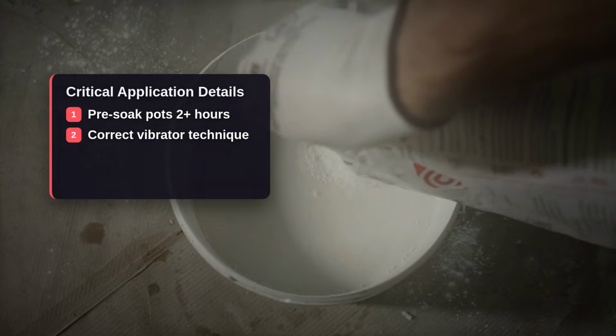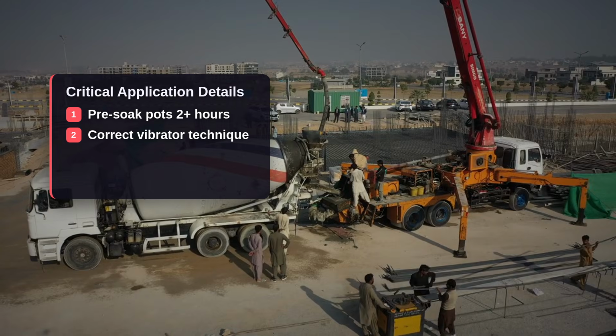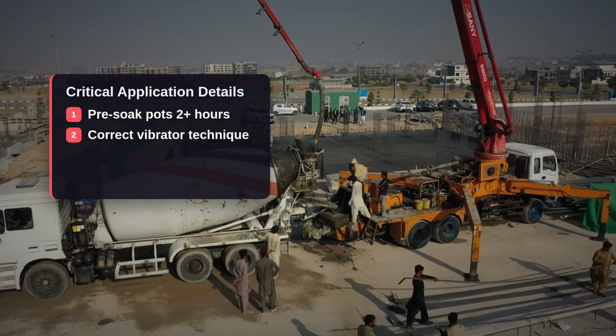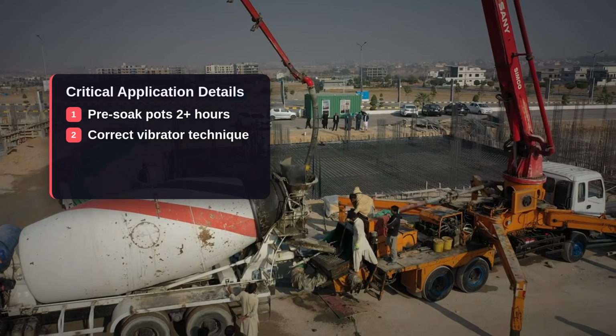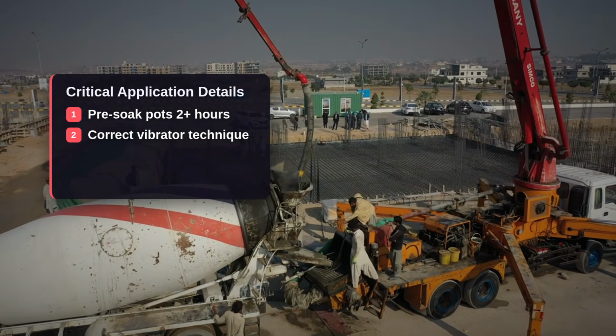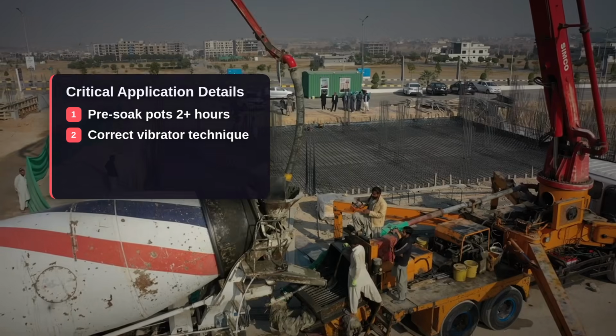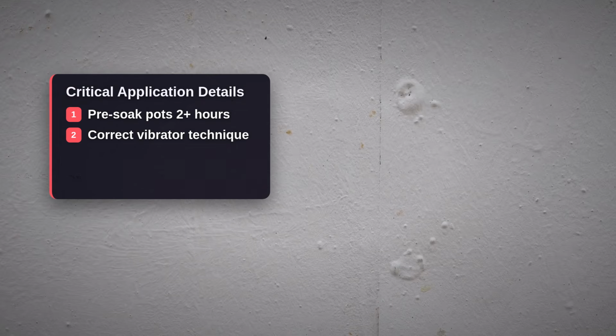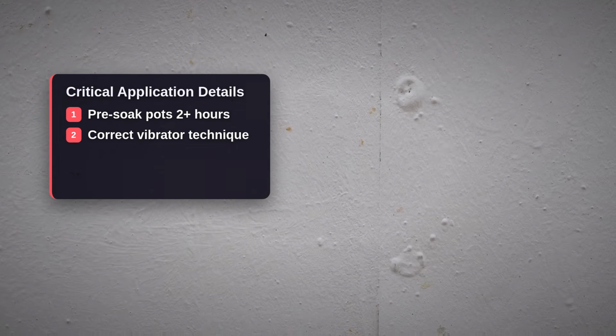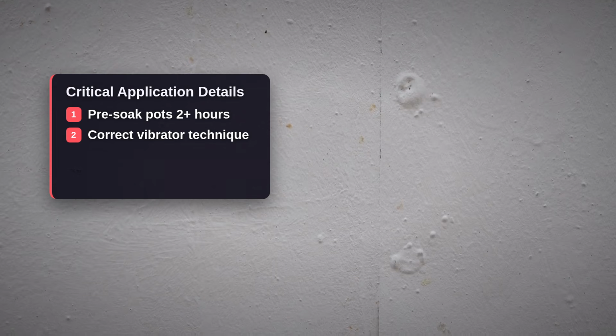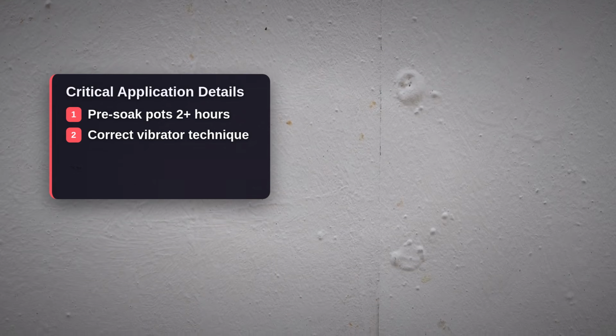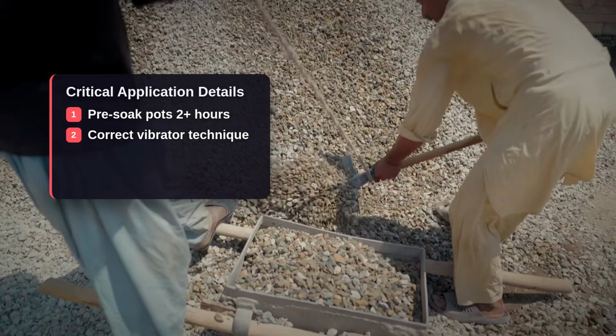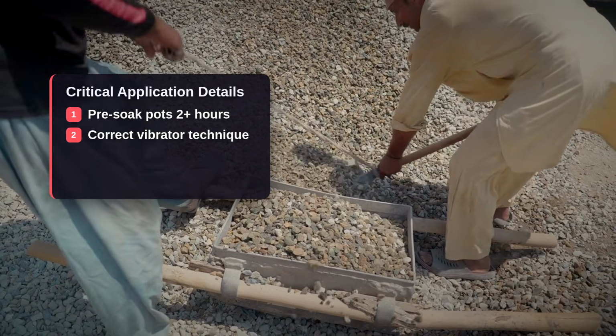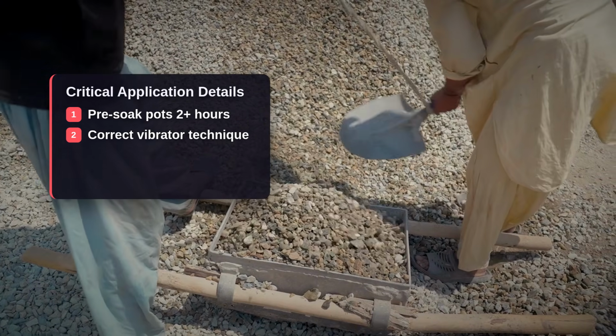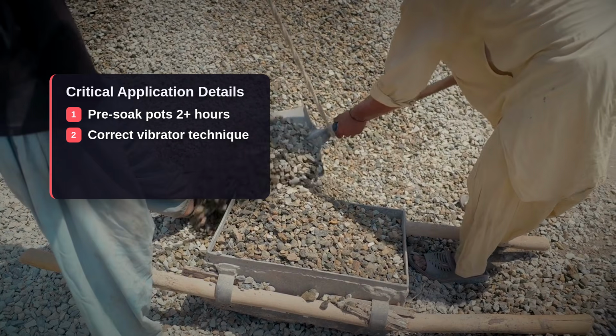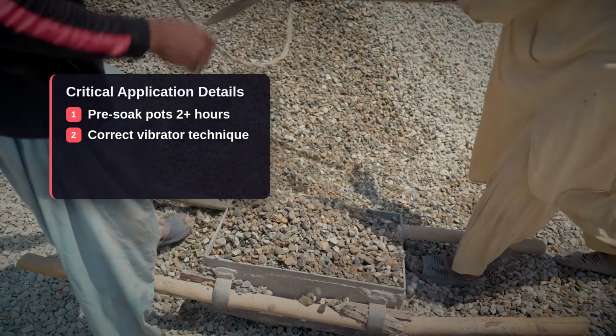The third error, and the one that quietly destroys long-term performance, is failing to seal the underside of the finished slab. A filler slab roof that is left with an exposed concrete soffit will eventually allow atmospheric moisture to enter the microcracks that develop in any concrete over time. Once moisture finds a path to the clay pot voids, you're looking at a slow evaporative cycle that, in humid climates, can lead to mold within the void spaces, and in cold climates, the freeze-thaw damage we already discussed.